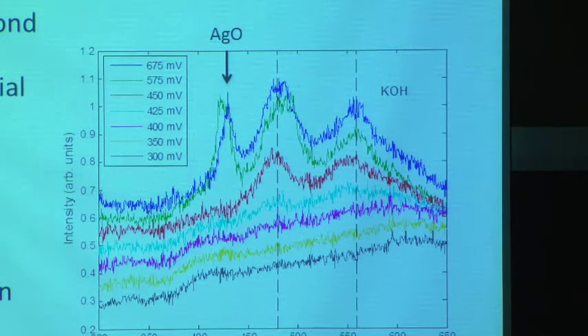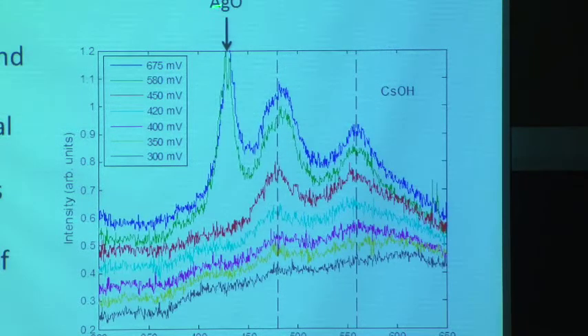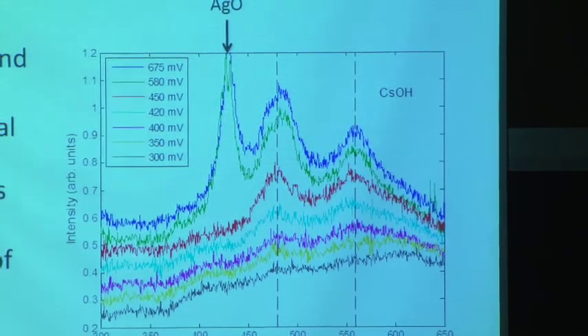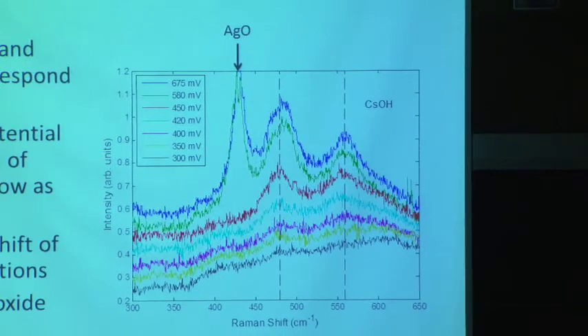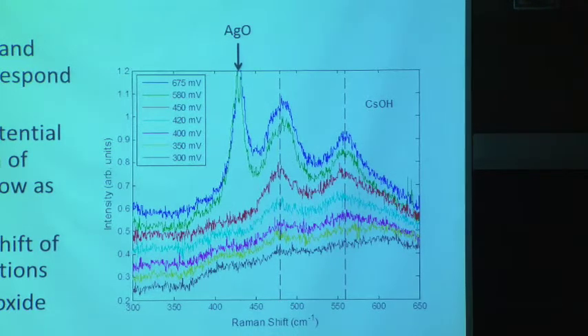And finally, in cesium hydroxide, you see a very, very large silver oxide peak and a very early onset of this phase forming. Right? So we see a further redshift, shifting to the left of these peaks here.